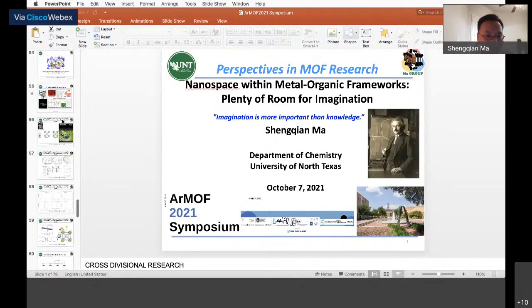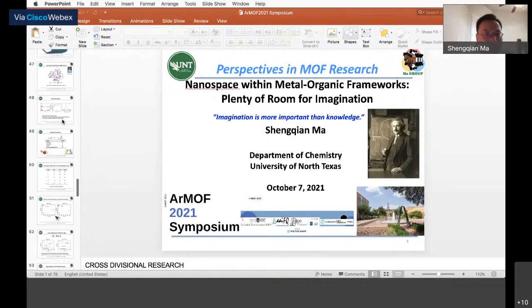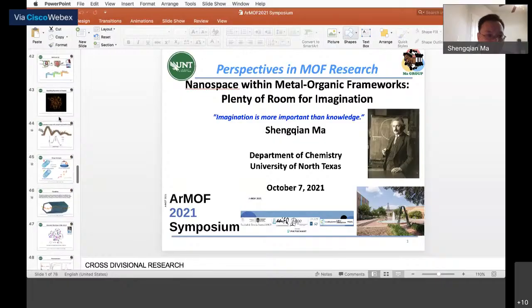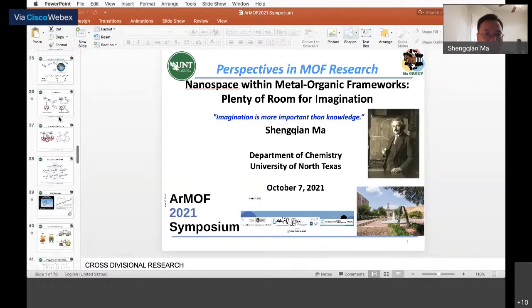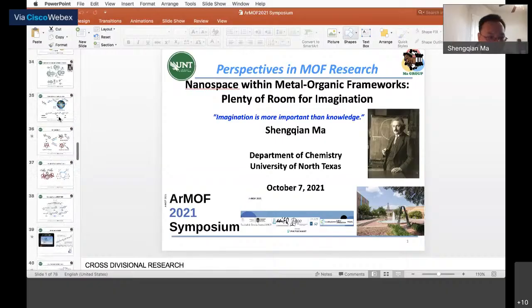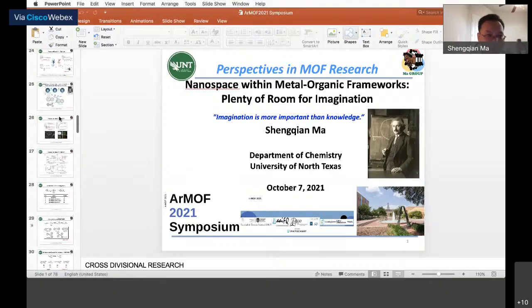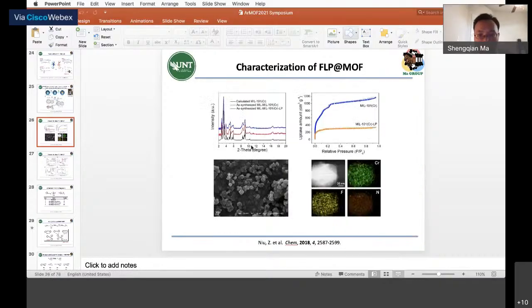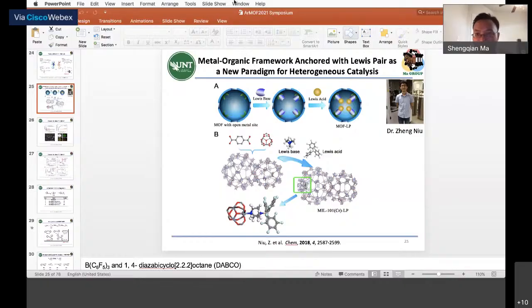We did the EDS, and also we did the fluorine mapping. Because of the distribution of this FLP in the MOF, I think it's very uniform, because it's not like we encapsulate another particle, right? To dope, we use anchoring. Basically we take advantage of the open metal sites, and we use them to stabilize. It's different from what other people do, where you just throw in the enzyme or another particle into it. Basically, ours are very site specific.